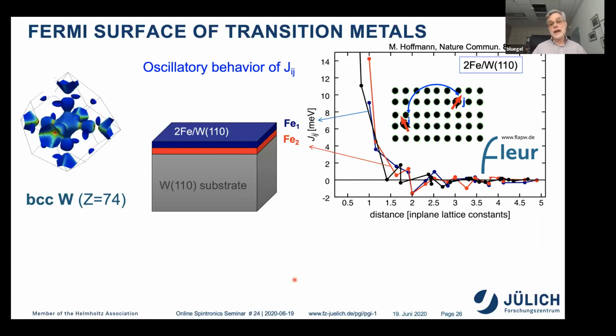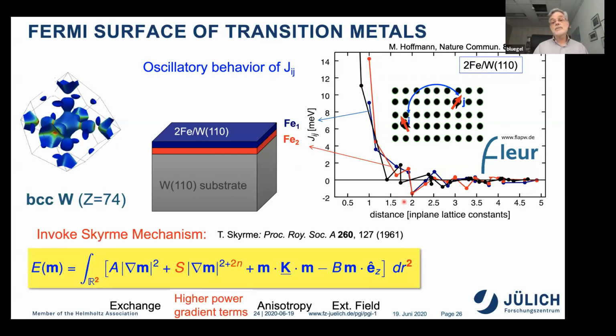And these long-range interactions are actually sometimes, like here, positive. That means they are ferromagnetic. Here red, for example, is this iron layer, and blue is this iron layer. And then you see at some distance they are negative. They are antiferromagnetic coupling. And in some regimes, it can happen that this leads to frustration. These competing interactions are not very easy to describe in a micromagnetic theory.